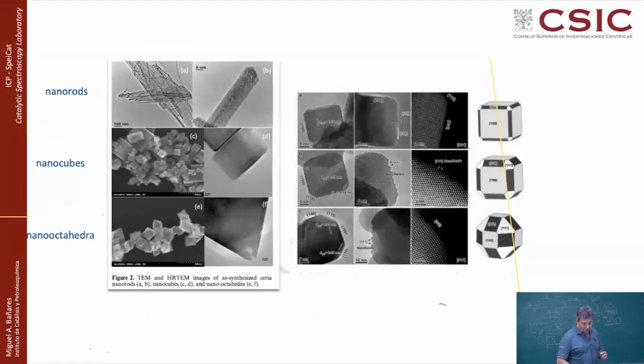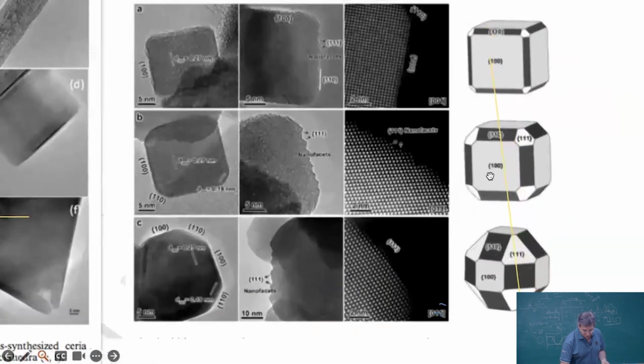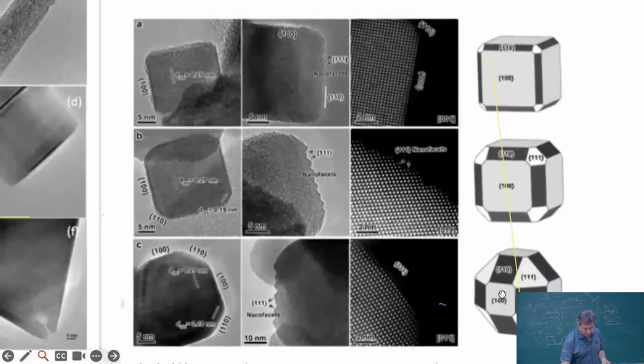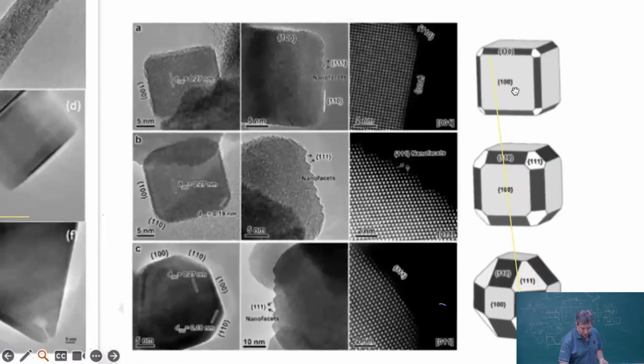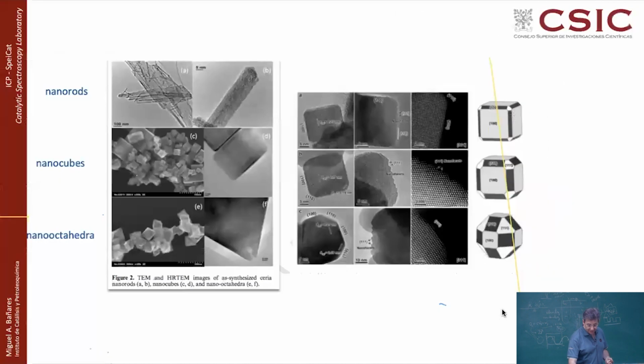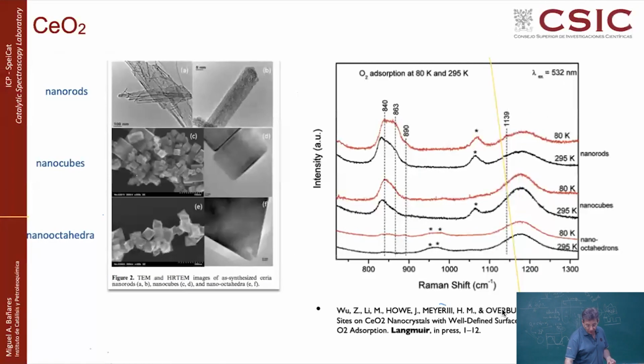And in general, as I told you, ceria is very special. You can modulate the performance of ceria. Ceria can be nanorods, nanocubes, or nano-octahedra. So the exposed face of ceria can be very different, like you see here. And you can do refaceting with temperature treatment and with many conditions. So all kinds of different ceria will have different reactivity, different kinds of sites. And that is also a way of tuning performance.